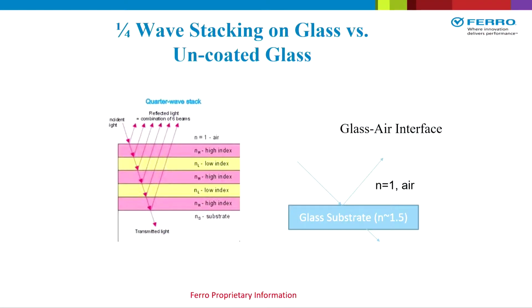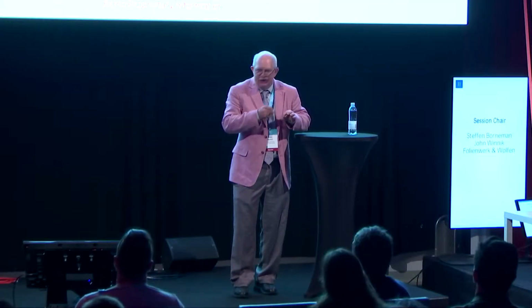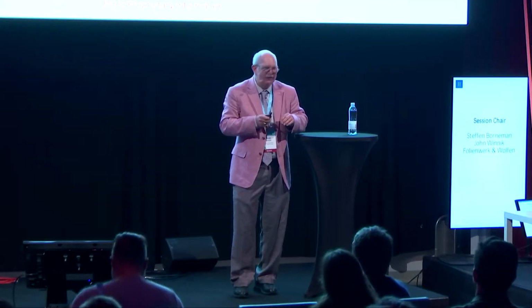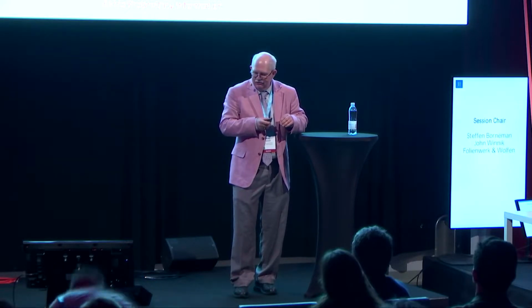And so this is just a description of the quarter wave stacking. You take alternating layers of a relatively high refractive index coating and a low refractive index coating, and you stack them on top of each other. What you want to do is have the thickness of those films be about a quarter of the wavelength of the light you're trying to reflect. So here it's about 80 to 90 nanometers that we want to make.